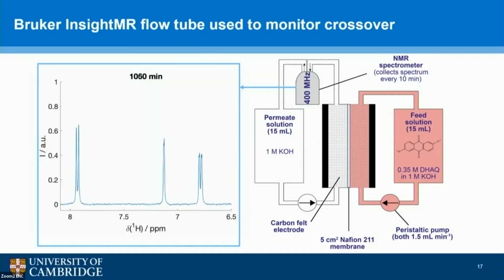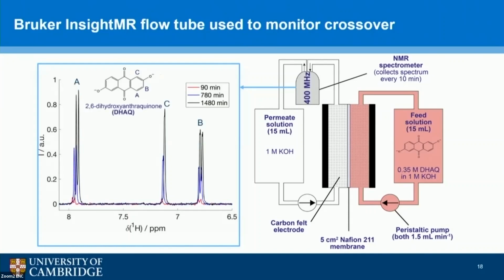This is some of the actual data that I've been collecting, and these 3 resonances correspond to quinone that's passing through from the feed side into the permeate side. You can see that over time we're getting an increase in the signal intensity, and you might also notice there's a shift to lower chemical shifts. This is related to intermolecular interactions at higher concentrations. But the main thing to take away is that we can see the increase in intensity.